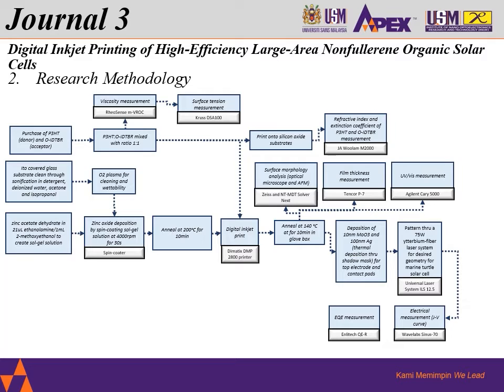So after the ITO is already done, the zinc oxide deposition was done by spin coating the sol gel itself on top of the substrate. And then it was annealed at 200 degrees Celsius. Before going to the digital inkjet printing, we have to prepare the ink first.